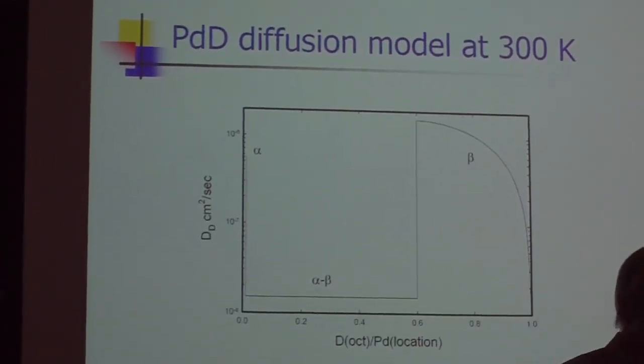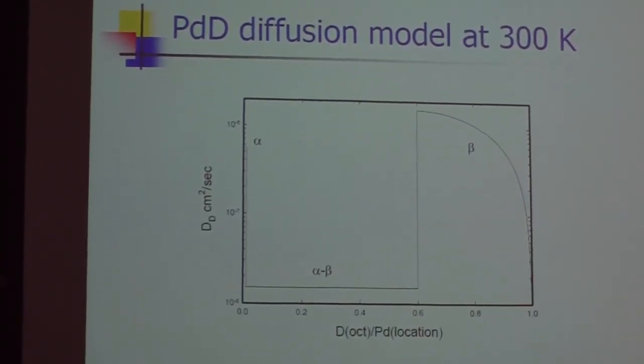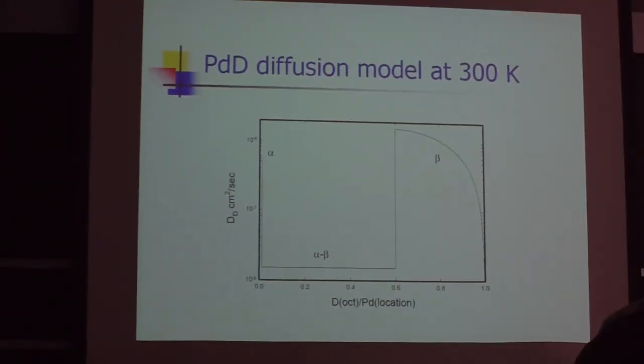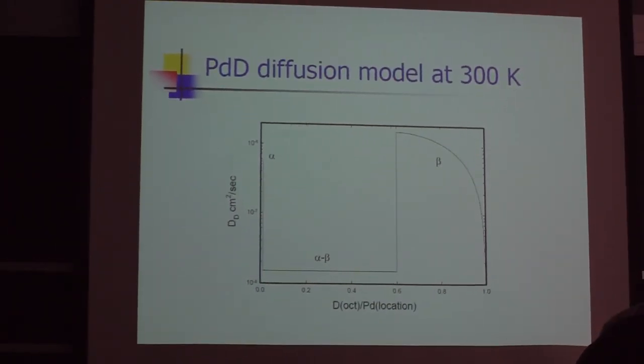I'm not sure what we're actually measuring in the miscibility gap because I think what you're dealing with there is two separate phases right next to each other. So you would have diffusion in phase alpha and phase beta, not some alpha-beta phase. So you'd have one average of both. I'm not sure what single value you're measuring in the middle of the miscibility gap.